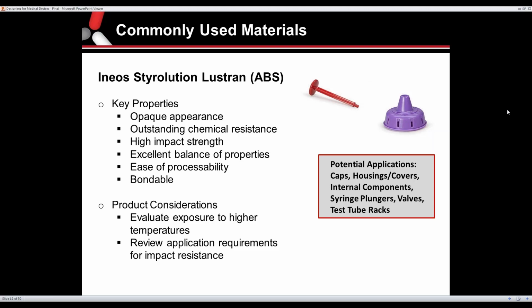So caps, internal components, valves, even labware, you can look at things like test tube racks, but also good with housings and covers. But because it runs at a lower temperature, you just need to consider the end-use temperature ranges to make sure that you're not getting too close to the heat deflection temperature so that it doesn't start warping on you. And then take a look at the impact resistance and make sure you don't need as high an impact resistance as polycarbonate would require of this material. But overall, great fit for the medical industry.